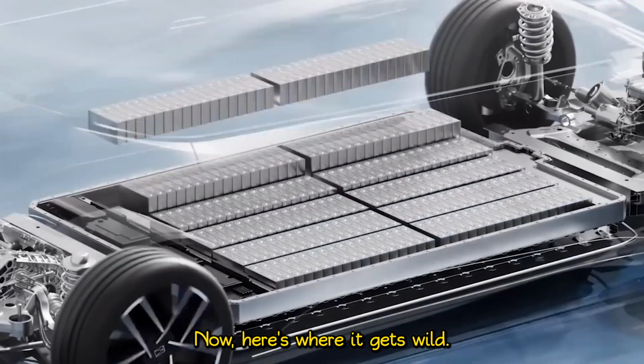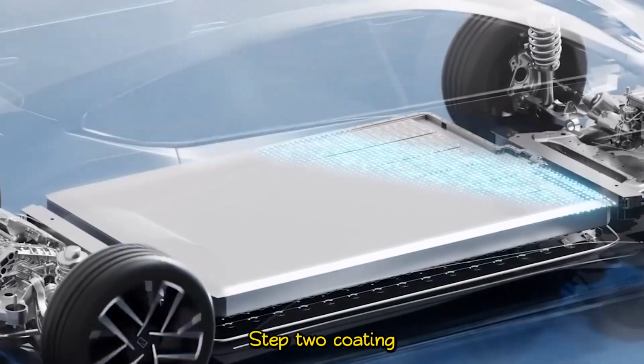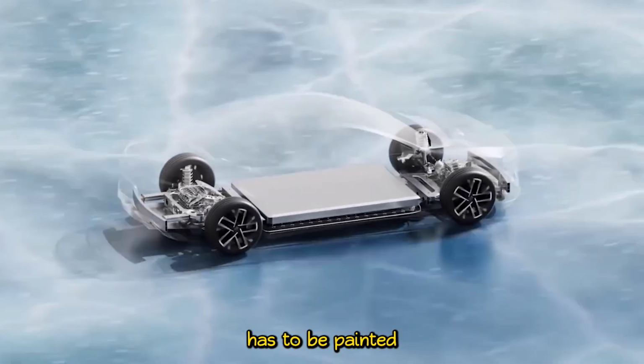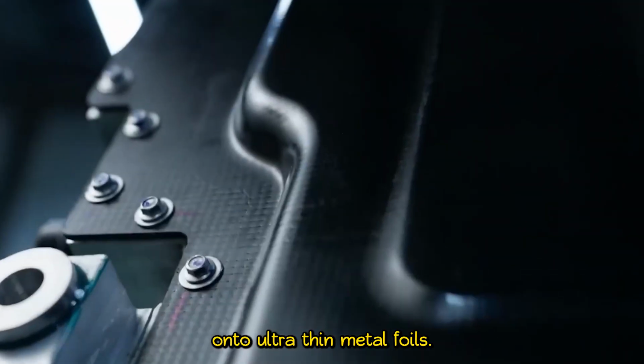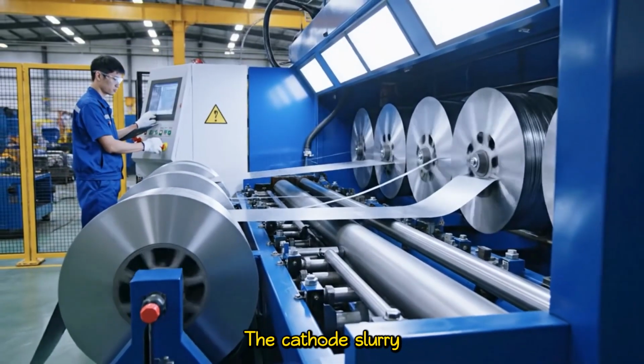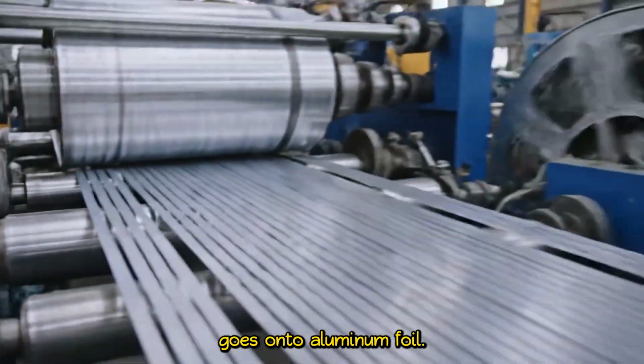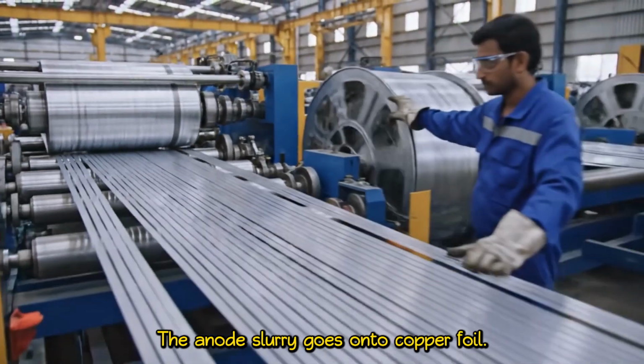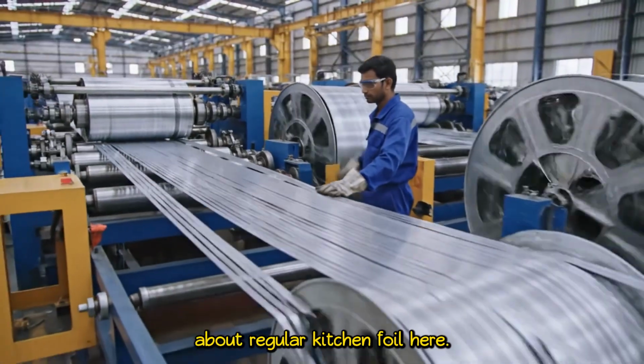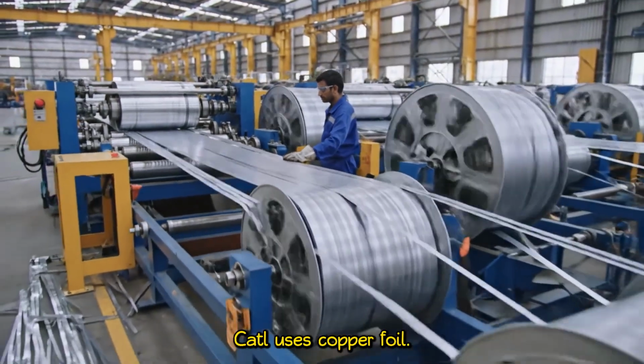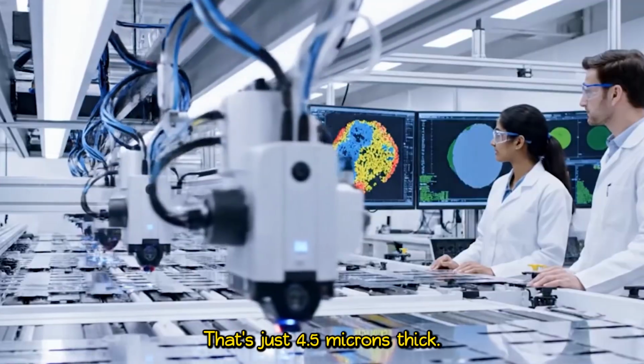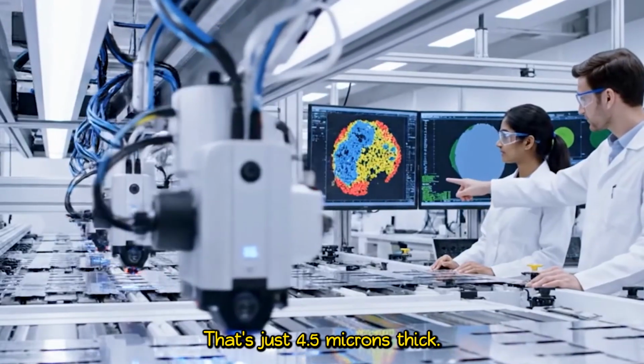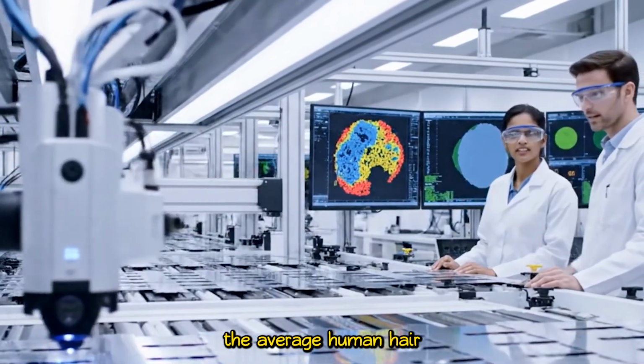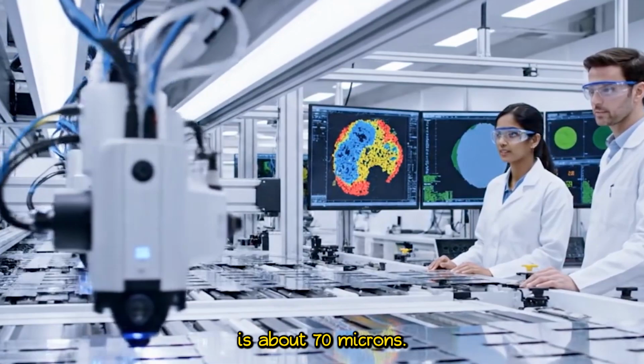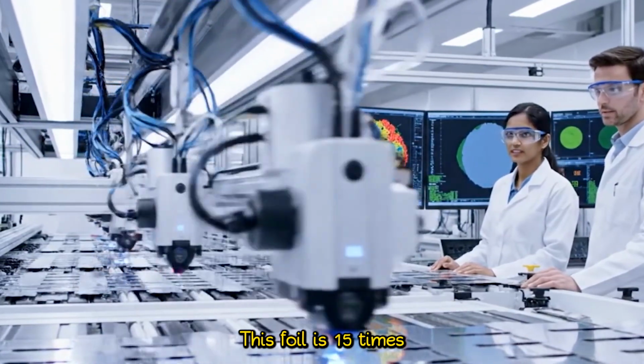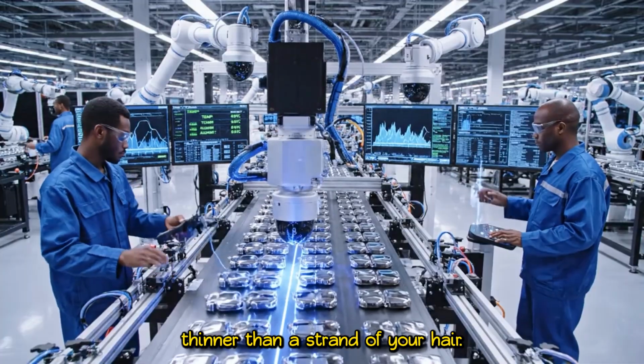Now here's where it gets wild. Step 2. Coating. That slurry now has to be painted onto ultra-thin metal foils. The cathode slurry goes onto aluminum foil. The anode slurry goes onto copper foil. And we're not talking about regular kitchen foil here. CATL uses copper foil that's just 4.5 microns thick. To put that in perspective, the average human hair is about 70 microns. This foil is 15 times thinner than a strand of your hair.